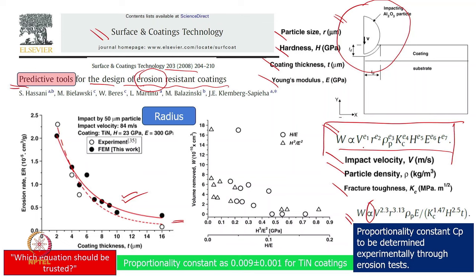Like in this case, particularly, they show velocity to the power 2.3, so this is a power law, while the radius effect is 3.13, which is much higher. Even if I assume it's spherical, it should be 3 only. However, they have shown 3.13. Density is proportional, Young's modulus is proportional. Now here the question comes: we are increasing the Young's modulus, but wear volume is increasing. So this is also important.